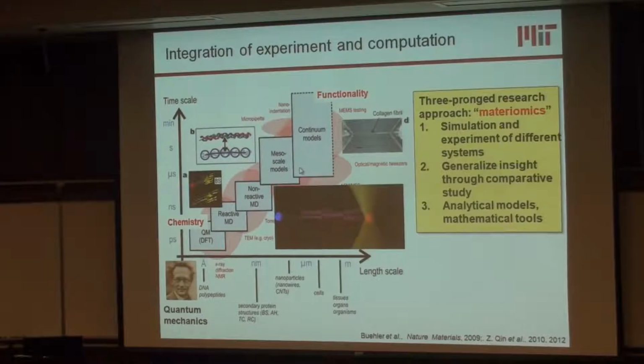If a force field doesn't exist, we do some DFT calculation to implement those interactions. Then we do classic MD simulation, also some combination of MD and molecular Monte Carlo simulation, like replica exchange simulation. We characterize its mechanical property, and we scale up to the continuum level.